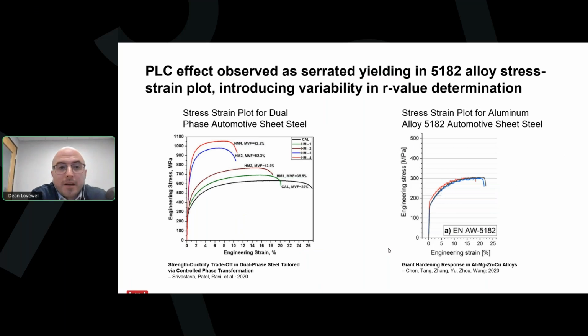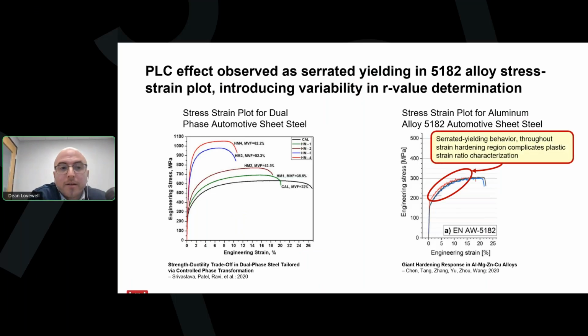And we see that effect here in the plot of this 5182 aluminum on the right, in contrast to the stress strain plot of the simpler dual phase automotive steel on the left. Now, the Portevin-Le Chatelier effect reveals itself just after yield, and in this 5182 aluminum, it continues all the way through tensile strength. Since this is the region where formability is characterized, it introduces significant variation to the calculated result, depending on which points are included in the calculation.